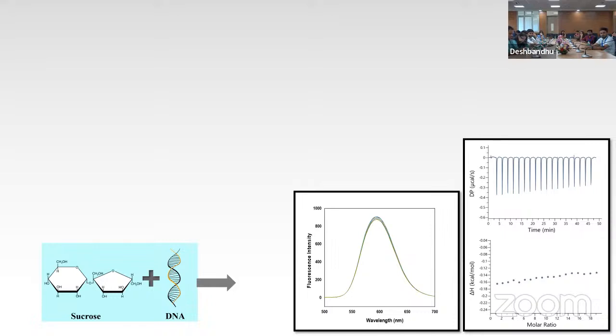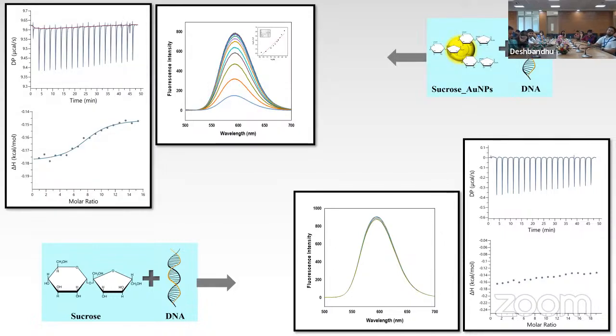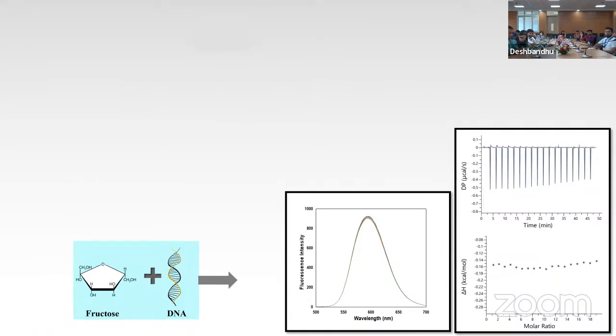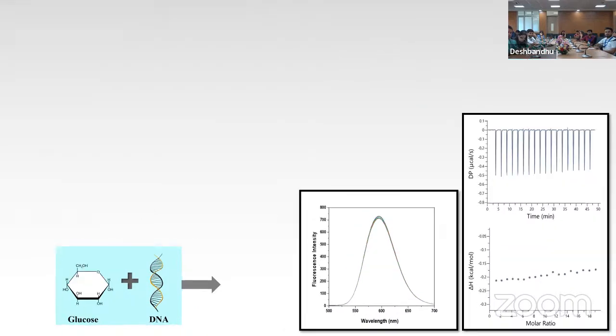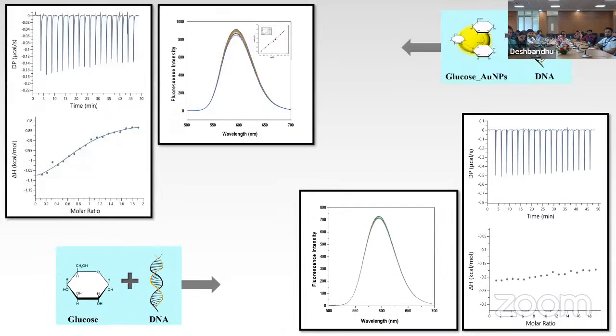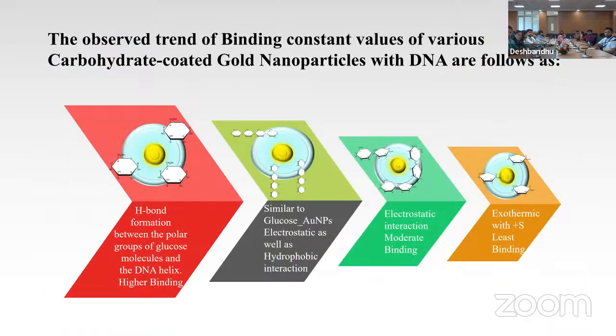So this is the profile for pure sucrose and sucrose coated gold nanoparticle, pure fructose and fructose coated gold nanoparticle, and glucose coated gold nanoparticle. The observed trend for various carbohydrate coated gold nanoparticles with DNA is as follows: glucose shows higher binding, and starch shows similar binding to glucose, sucrose shows moderate binding, and fructose gives the least binding because of the keto group.